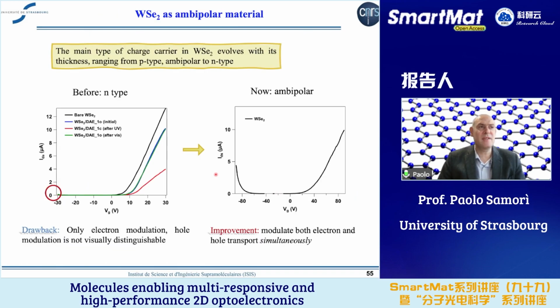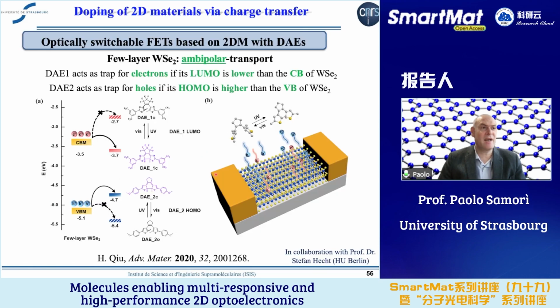Now, you can, of course, use tungsten diselenide also in the condition where it behaves like an ambipolar transistor by changing the thickness of the tungsten diselenide. I have no time to go into the details. I'm just going to show you the approach that was based on using not only the diarylethene derivative that we used so far to trap and untrap charge transport, electron transport, but also we have designed a different type of diarylethene whose HOMO levels are either in the band gap or out of the band gap if one considers the valence band of the tungsten diselenide. Therefore, we can also trap and detrap at the HOMO level, therefore the hole transport.